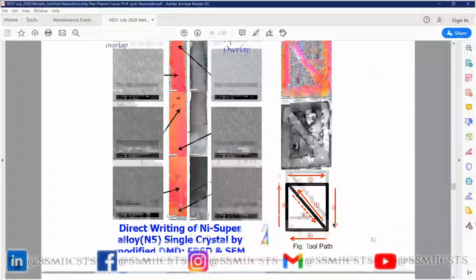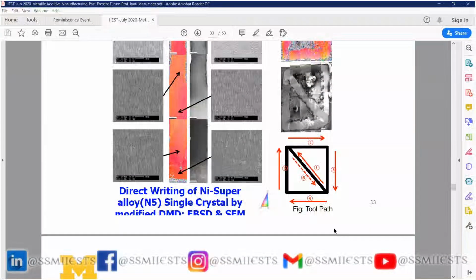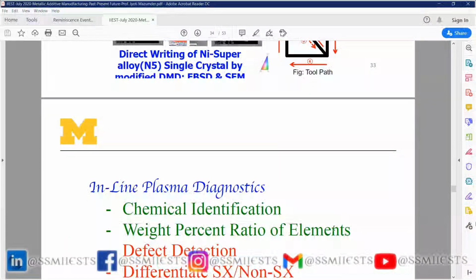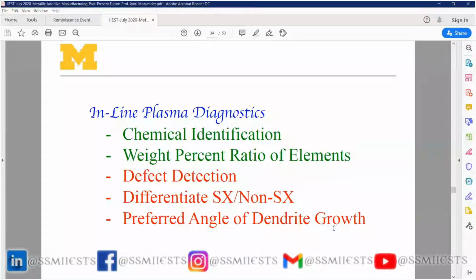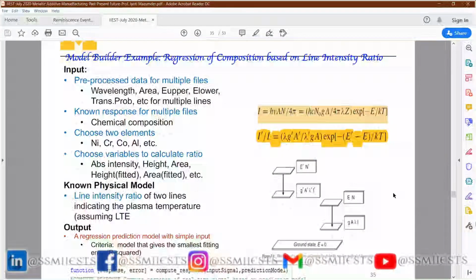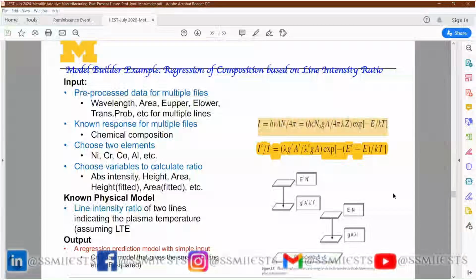But what you can do to ensure a single crystal doesn't have any defect. So things you try to look at: what is the chemical identification, whether I know the composition, what percent ratio of the element, defect detection, differentiating between single crystal and non-single crystal, and preferred angle of dendrite. All those you can find out from the information in the plasma. And we basically developed a regression model for composition based on the line intensity ratio. And using this equation, we can essentially estimate what is the composition of the material we are putting.